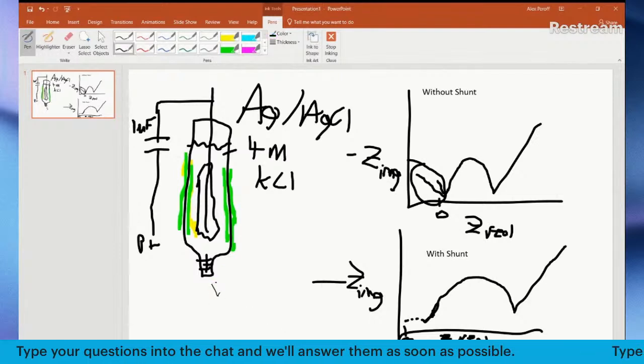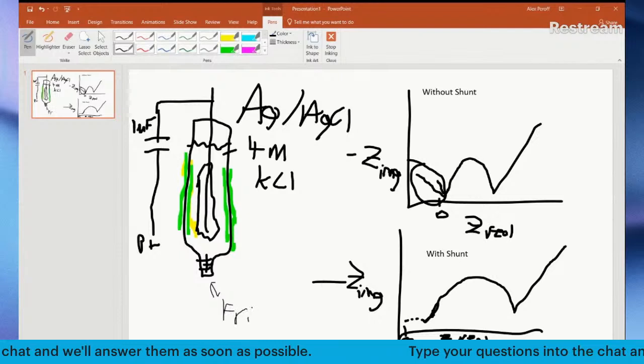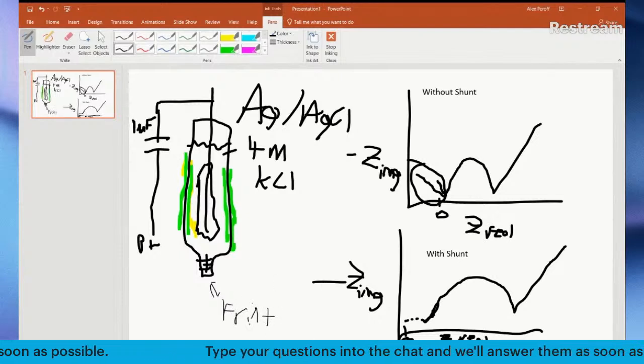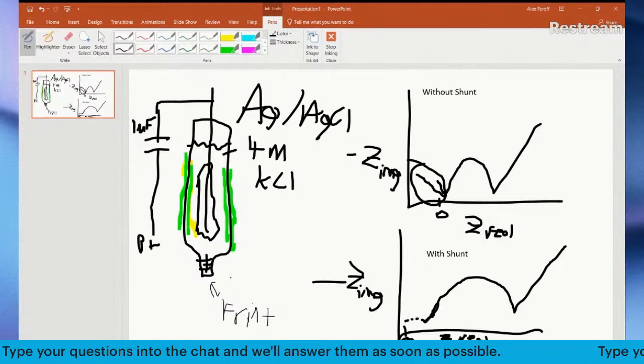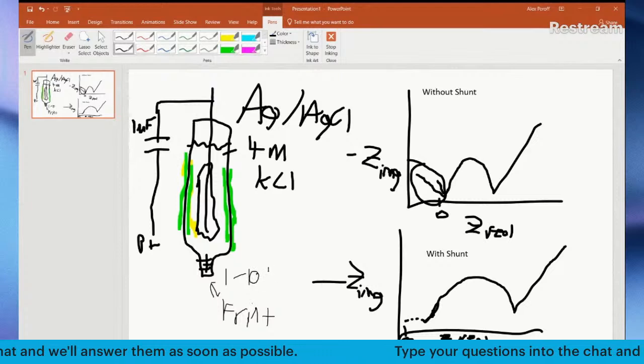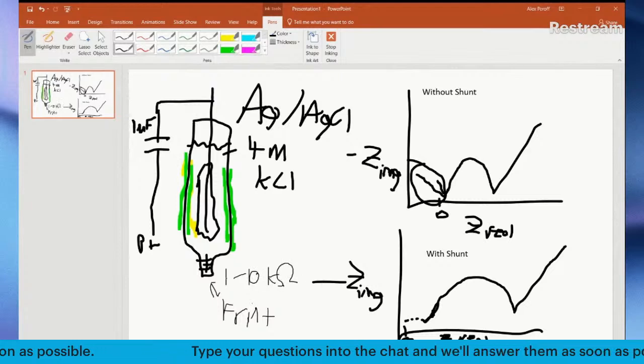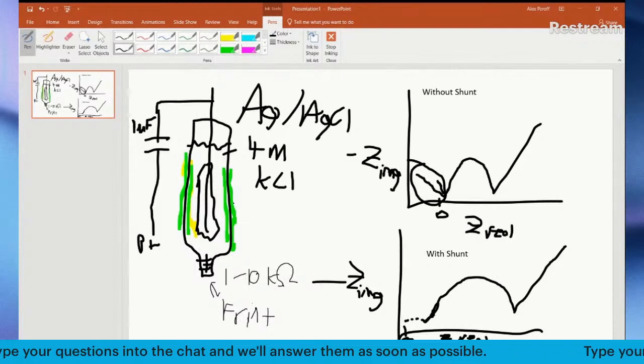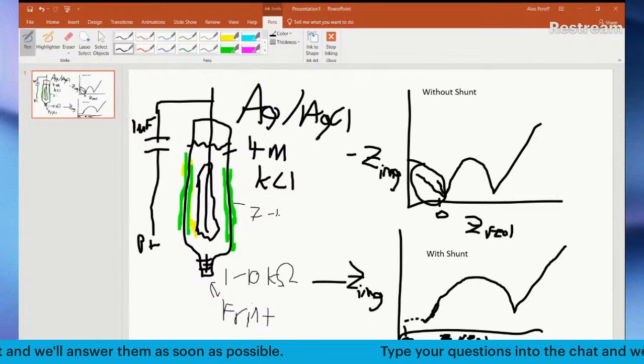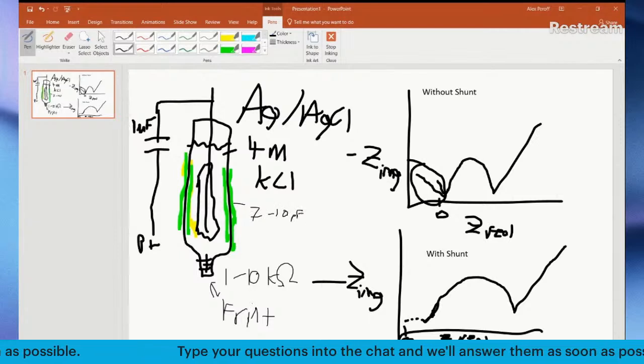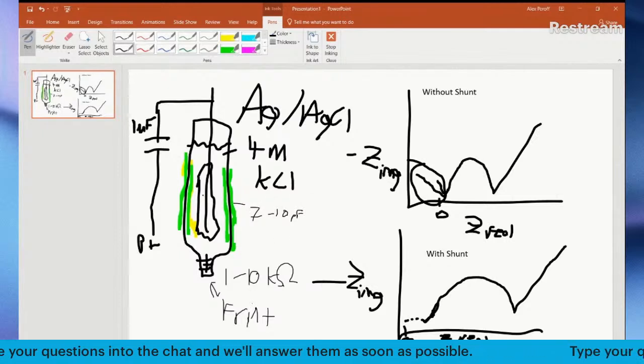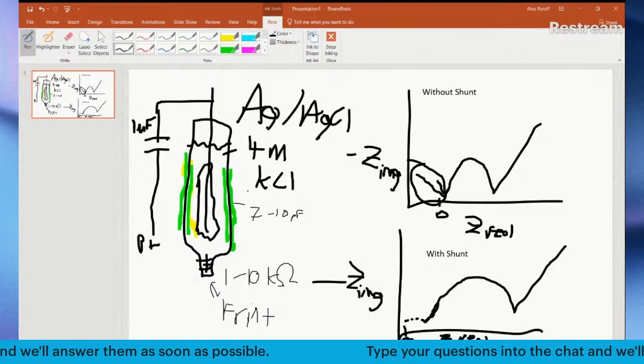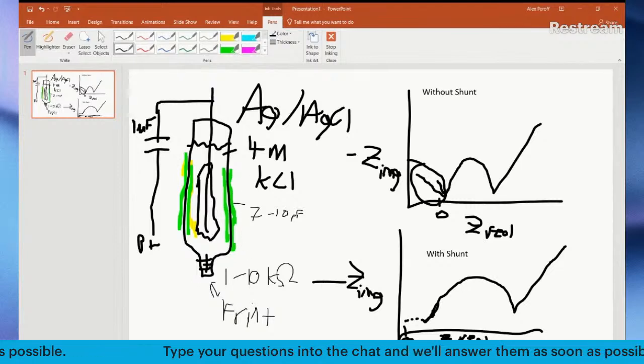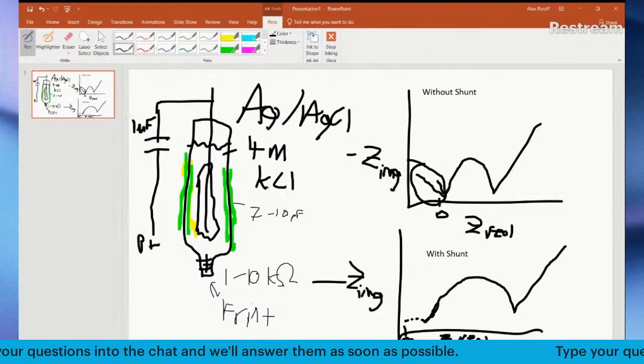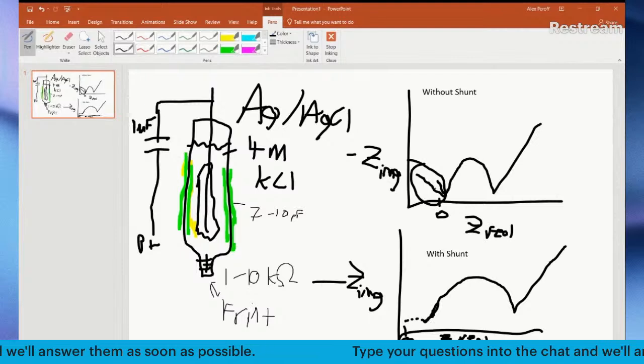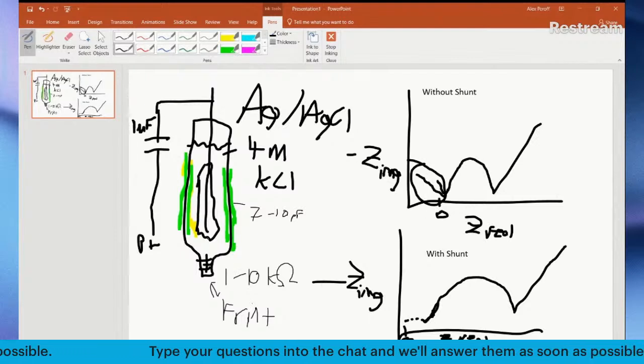And then on top of that, this frit can have a very high impedance, somewhere on the order of maybe 1 to 10 kilo ohms. So these can be very resistive. And between this, again, 7 to 10 picofarads, in parallel with this frit, you create what's known as a low pass filter, and it just so happens that this will cause phase delay at the high frequencies when you're doing EIS.